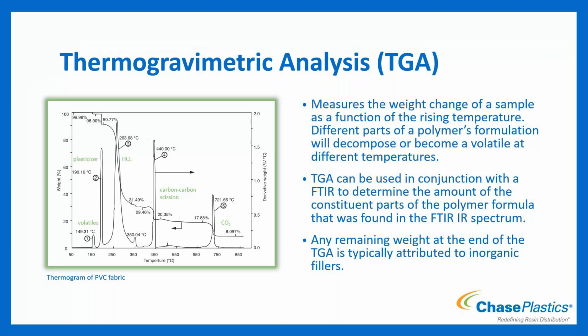And so if we've noted that maybe it's a PC/ABS that's in there, your TGA would be able to maybe tell you, here's where your ABS is burning off, the PC portion. If it's a filled material, you'd be able to tell whatever's left over. So the last bullet, remaining weight at the end, is typically attributed to inorganic fillers. So stuff like your glass would be left afterwards. So you'd be able to tell how much of each is in there and then how much of your glass is in there.